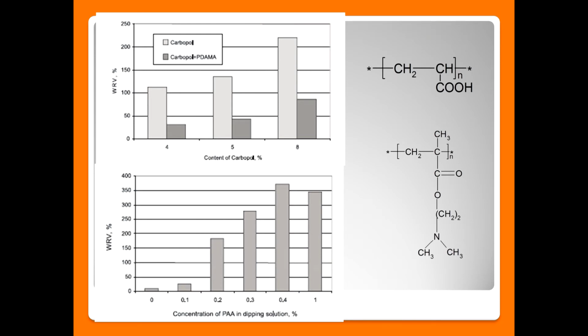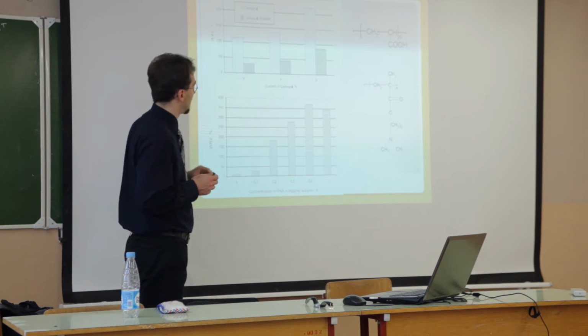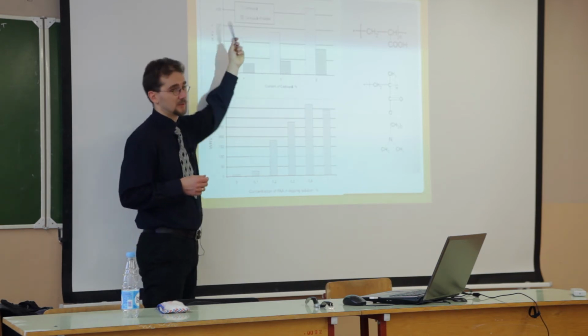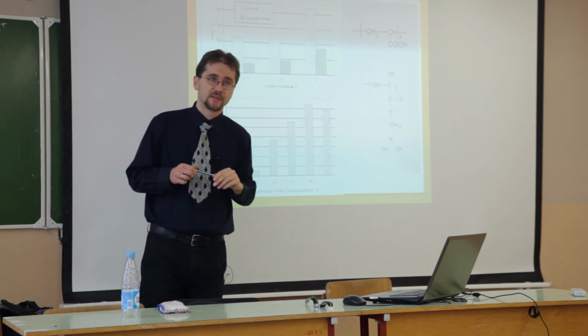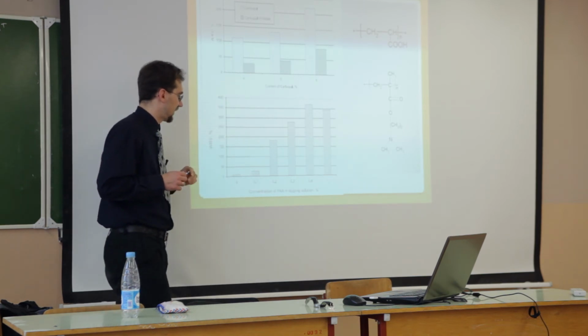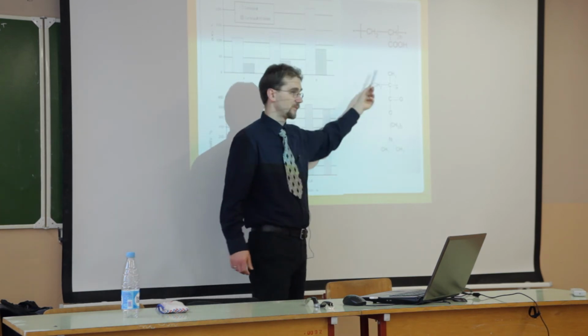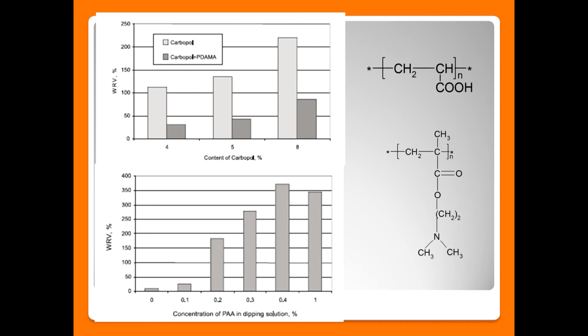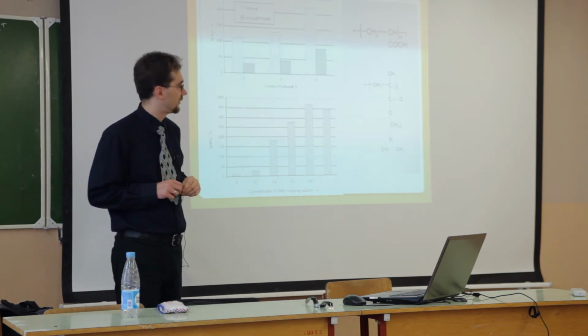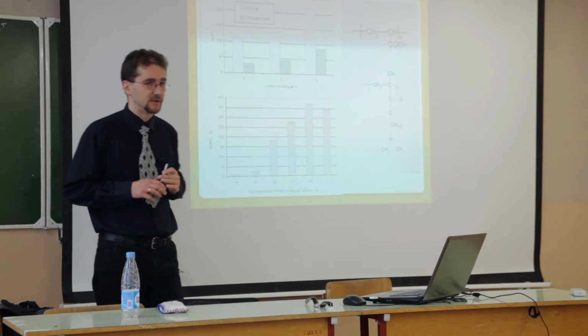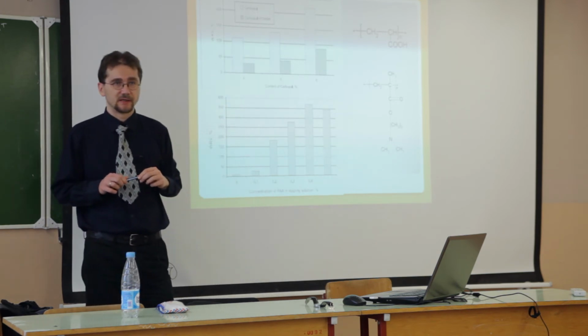Again, creating a multi-layer structure, the first layer is polyacrylic acid with the commercial name carbopol. It is partially a cross-linked polymer, and as a second layer, we introduce this polymer. I would like to say a couple words about that polymer. We called this polymer with the acronym PDAMA. This is dimethyl amino ethyl polymethacrylate. Very interesting polymer, and I am working on this material for a very long time, and there will be a couple words about that material today, later.